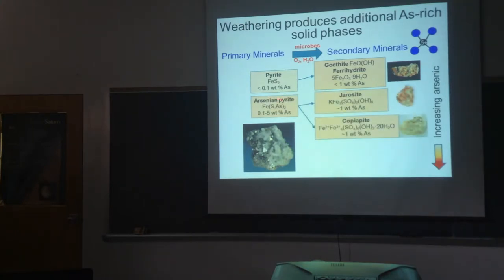When you get to the arsenian pyrite, again up to about 5% arsenic is, from my point of view, the maximum we've seen, say, at Empire Mine. And again, the arsenic substitutes for sulfur, so it has a net charge of -1. Arsenic can go all the way down to -3, and sulfur can go down to -2 as the most reduced form. But as you may know from pyrite, the sulfur has a net charge of -1, and two of them balance off the +2 in the iron. So the arsenic is also in a -1 form when it's in pyrite.